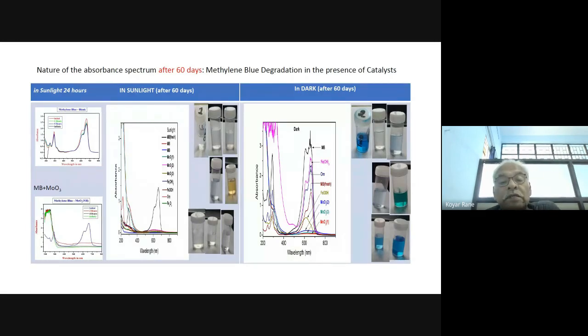Well, for a simple laboratory purpose, for the students who want to work on that one, you can see that methylene blue, when it is just exposed to sunlight for 24 hours, there is hardly any decolorization or degradation taking place. If I use the catalyst, almost 70 to 80% degradation can be seen on the UV visible absorption spectroscopy. Now, after 60 days, as I have seen, most of them are colorless, and the lambda maximum has come down almost 98%. So it says that there is a degradation taking place.